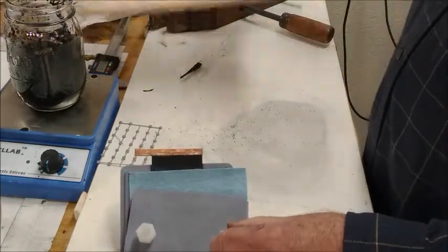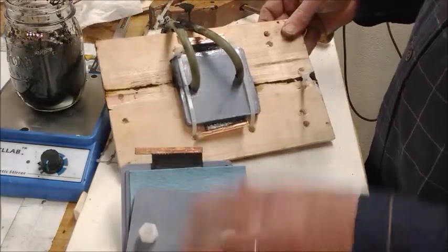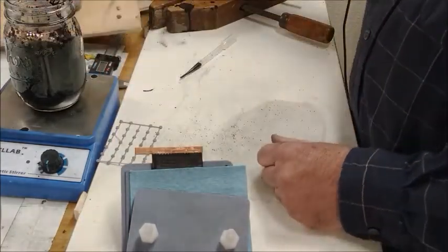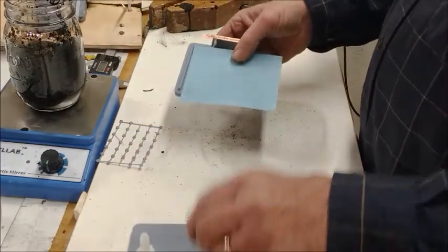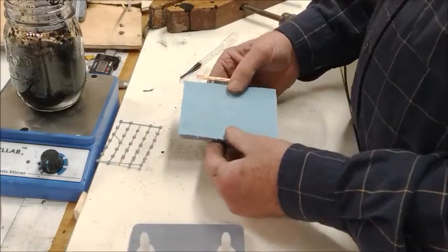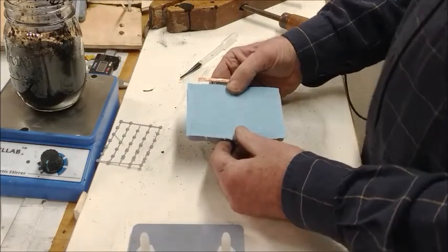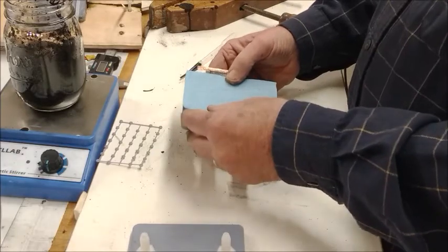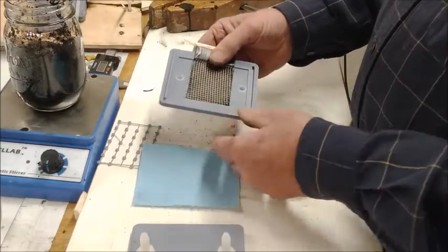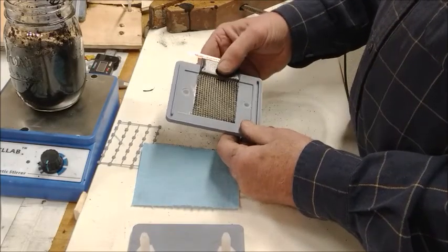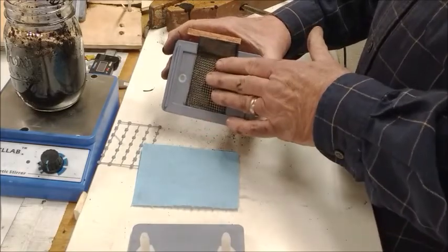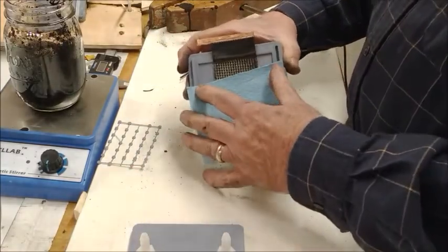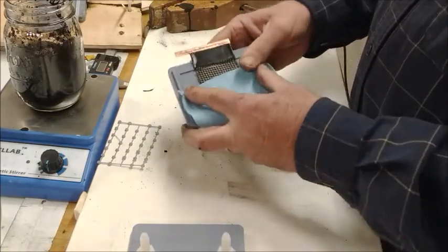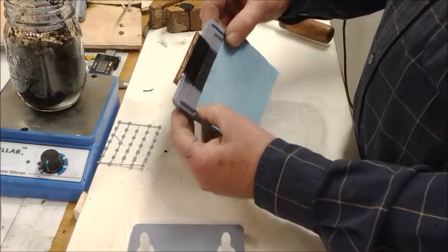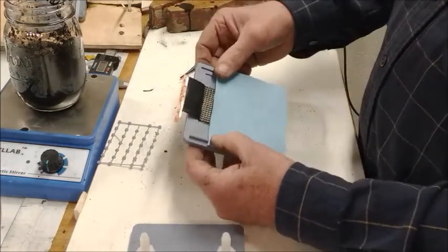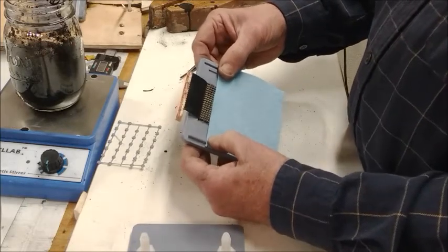That's where we ended up with this earlier design that worked fine as a static cell but had very poor flow performance. And what I found, not unlike what has been outlined in some of the research that's been done, is there's a fine line between the performance of the cell in terms of the many factors, mainly the gap that is formed between, in this case, the current collector and my paper towel separator. If I stretch that across this cavity, in my earlier cell, there was about 20 thousandths of an inch, about half a millimeter of gap.